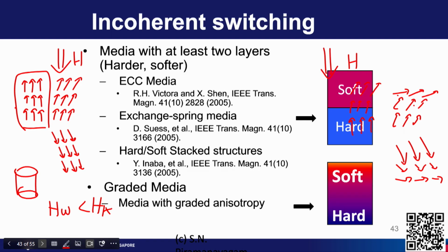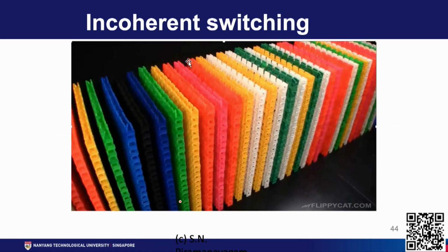So, we can achieve this by having materials with two different magnetic properties. For example, we can have a layer with an Hk of 20 kilo oersted at the bottom and 10 kilo oersted at the top. So, you see the anisotropy fields Hk of the two materials that we use are different, or you can have many layers, or you can have a gradual decrease from 20 kilo oersted to 10 kilo oersted. So, gradually changing and so on. Okay. So, this kind of material where you have many layers with a different anisotropy field, they will switch independent of each other. Okay. So, it is like a domino falling down.